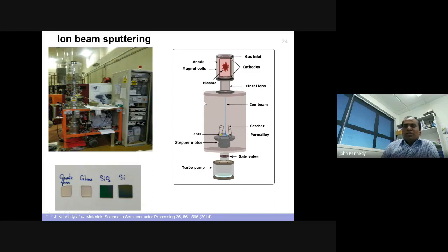It operates in high vacuum. We have a turbomolecular pump, so you can see the pressure is low. But we also have an in-situ gas feed system as an option, if you want to sputter under a nitrogen atmosphere or some specific argon atmosphere like that. So this is the one which we use, and you can deposit the films on any substrate. There is no problem with that.